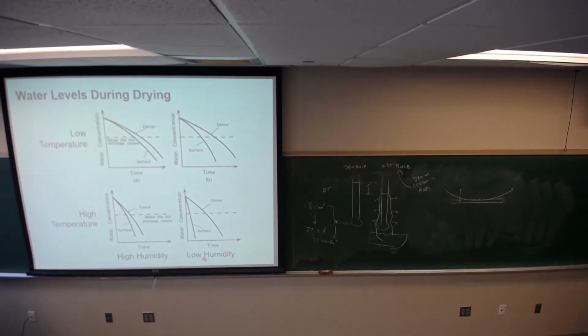This one is that essentially with low humidity and high temperature, you're going to see greater differences in the water content from interior to exterior of the body. These are extreme cases, right? If I go to low humidity and high temperature, I have my greatest differential possible. That means my moisture content on the surface will be low and the moisture content in the interior will be high. That is a recipe for failure. That's quite difficult to do.